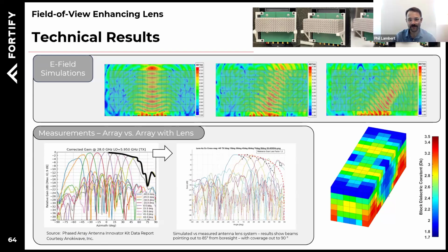And then with our field of view enhancing lens, you can see that black line right there is the phased array without the lens behavior. You can see that we've got some beams here at 80, 85 degrees from boresight. So using this device, we can create beams that point out to 85, 90 degrees to help to reduce the need for as many phased array units deployed to a field to cover the same type of area.